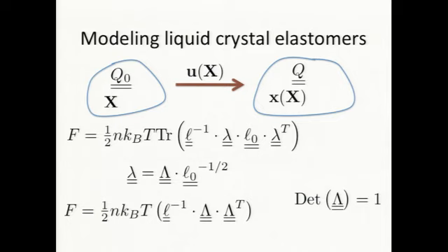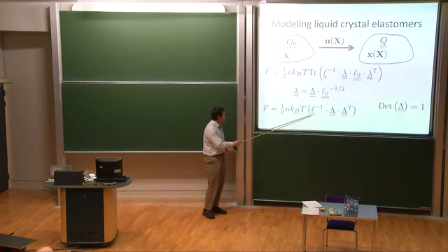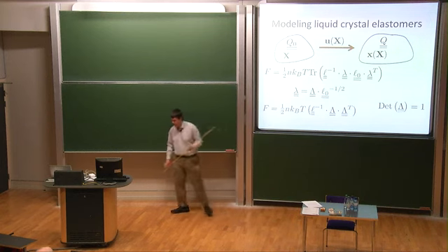And this is an important microscopic result, which says that even if you cross-link in the nematic state, where on symmetry grounds you didn't have a reasonable expectation where a soft mode should exist, in fact there is still an isotropic reference state you can write everything with respect from. You still see the full symmetry structure, you still see the soft mode. So you don't destroy it if you cross-link in the nematic state.